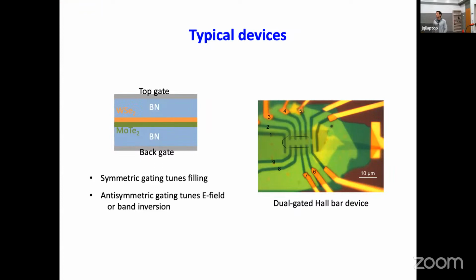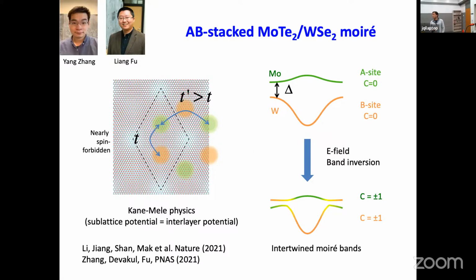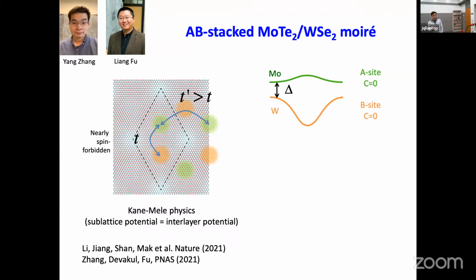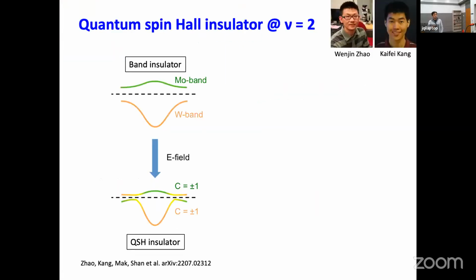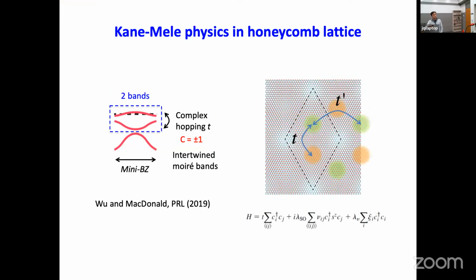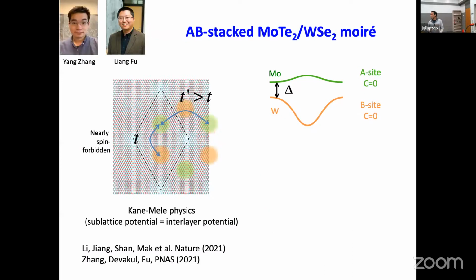So, was the AB stacking required for this type of physics? The question is whether AB stacking is really required. For this theoretical proposal, for instance, they are not considering AB stacking, they consider AA. I think what's really needed is a two-layer system. Then the electric field can tune the potential difference between the two layers, and if the Wannier orbitals happen to occupy a honeycomb lattice, that corresponds to changing the A and B sublattice potential. So AB is not really required, but experimentally, we so far only found one example, which is AB, that works well to have this band inversion and the introduction of topological bands. But I don't think it is required.